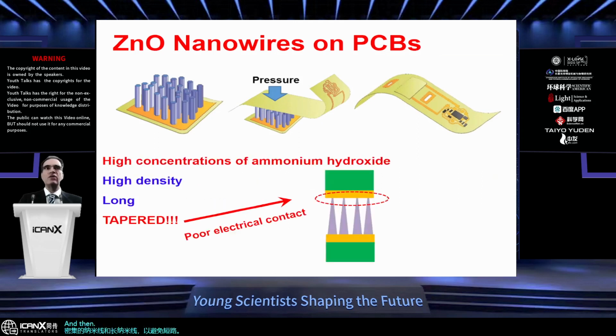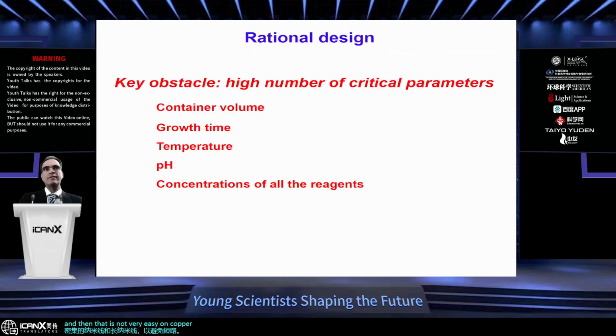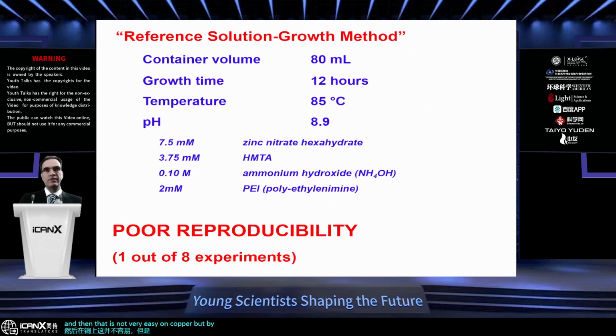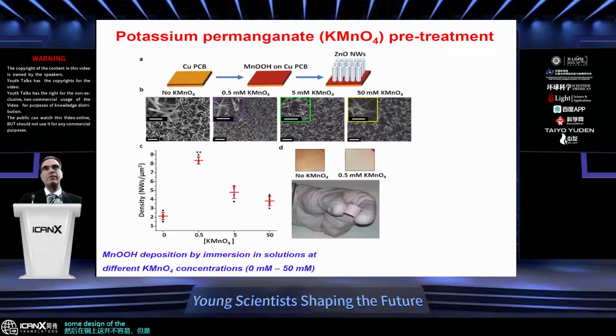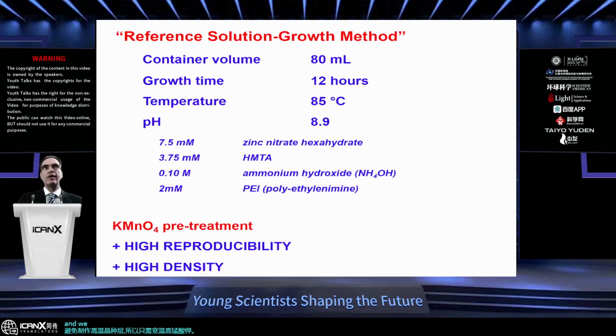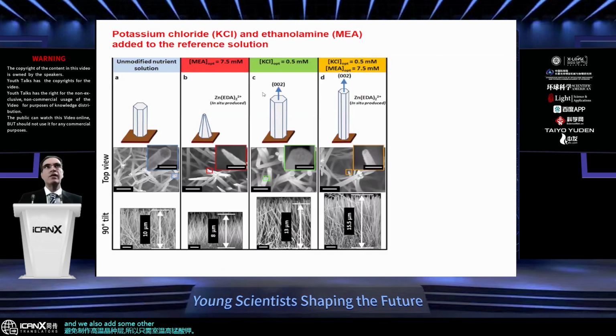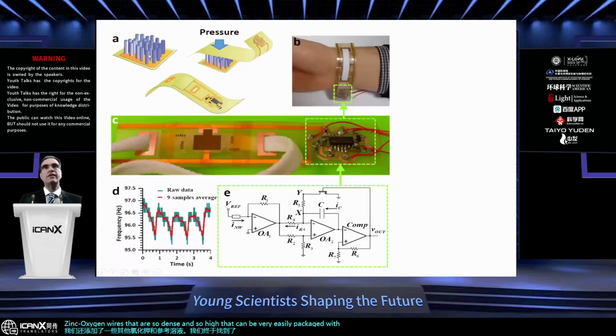And that is not very easy on copper, but by some design of the wet chemical processing, particularly by using potassium permanganate to avoid the fabrication of high temperature seed layers. So just room temperature potassium permanganate. And we also add some other potassium chloride to the reference solution. And we finally find zinc oxide nanowires that are so dense and so high that they can be very easily packaged with the approach that I just suggested.